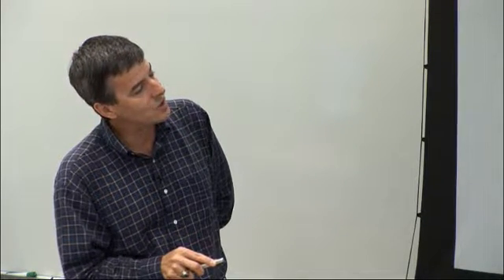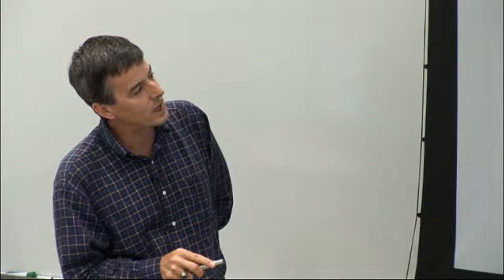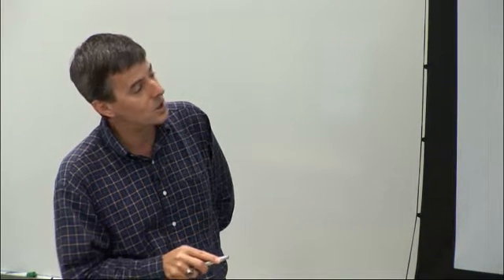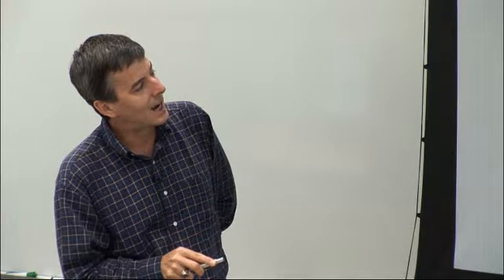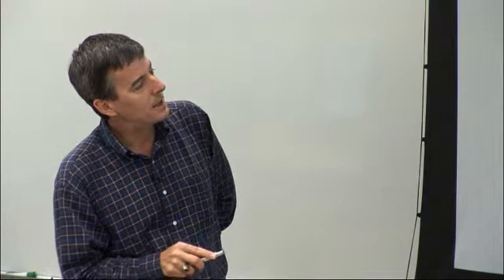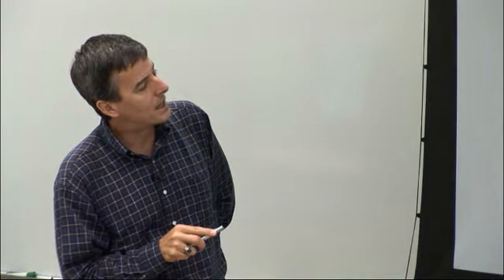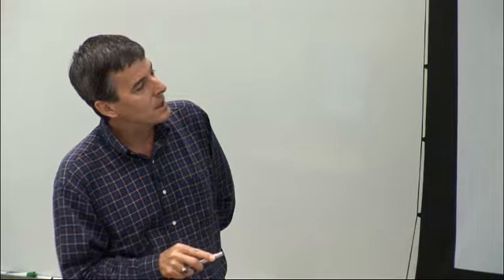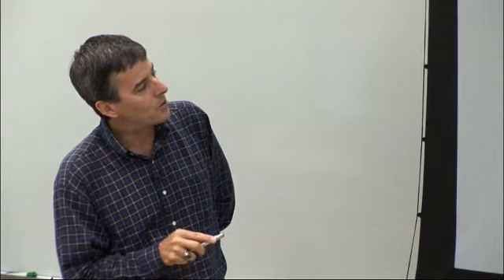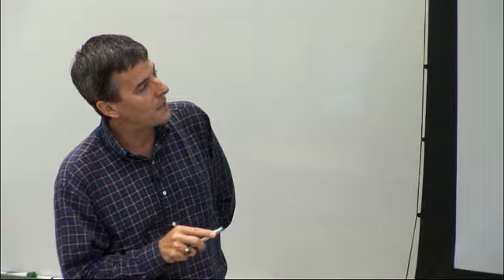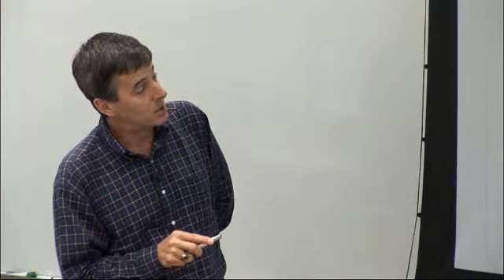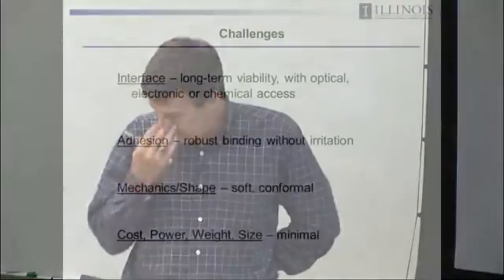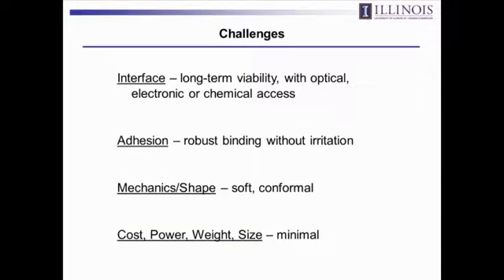It needed to be at least as stretchable as the skin itself. So skin will stretch to about 30% before it starts to tear. So we want something that would have that kind of elastic level stretchability. And then some additional requirements. You need your sensors and electronics electrically isolated from the skin, so it needs to be waterproofed, but at the same time you don't want to disrupt natural processes of transepidermal water loss, so you need some level of permeability as well.